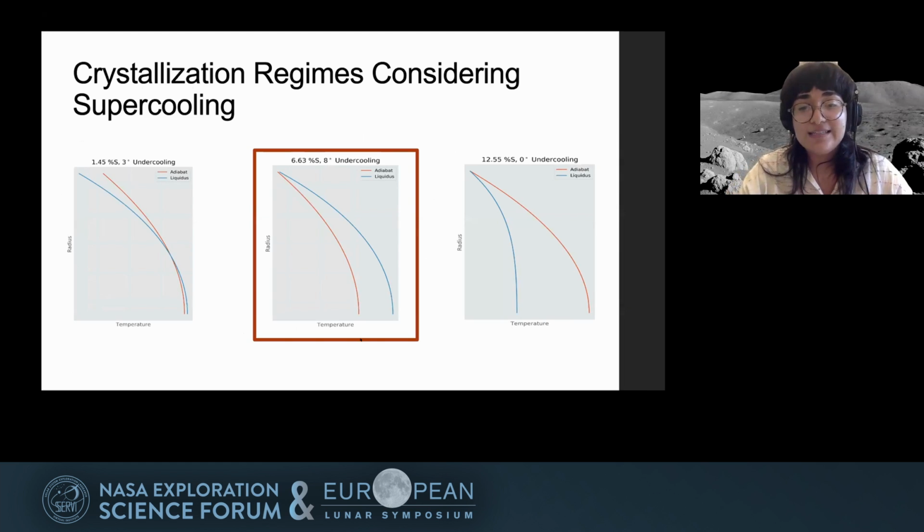We see that only 8 degrees supercooled the entire lunar core, which means that if a substrate is present at the CMB, solids will form at the CMB and not at the bottom of the core, as you would otherwise believe for a core with this given composition.